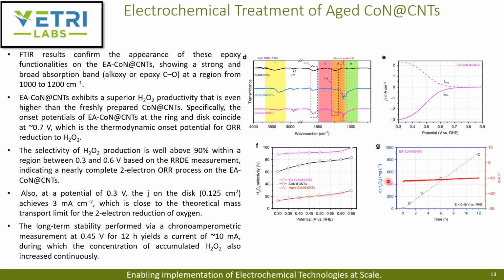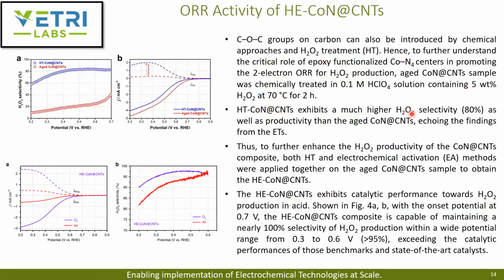One other thing to note here is that this current density is about 3 milliamperes per square centimeter, which is very close to the theoretical mass transport limit of the 2-electron reduction of oxygen. Then they examined the overall activity of the peroxide-treated sample. That was the other treatment to introduce these epoxy groups.